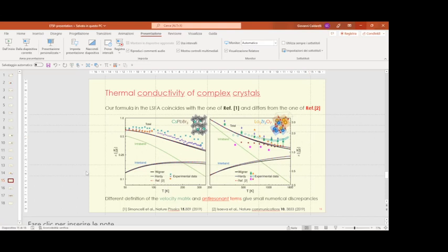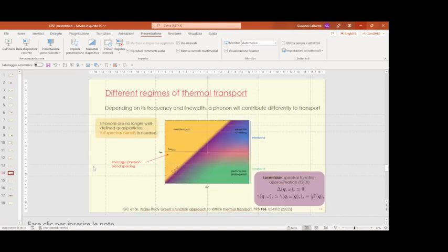So the idea is that you are in the overdamped regime when you cannot safely associate a quasiparticle peak with your spectral density, because the spectral density is so broad. This can happen if you have large broadening, but also if you have a multimodal spectral density. For example, it is the case of satellite peaks, which I think can also happen in electronic Green's functions, so in the spectral density of electrons. There is also an equivalent of satellite peaks for the phonon case. In that case, it is not safe to do a Lorentzian spectral function approximation, which is basically a quasiparticle approximation for the phonon mode, because there could be cases in which you cannot safely associate a spectral density with a particular phonon vibration.